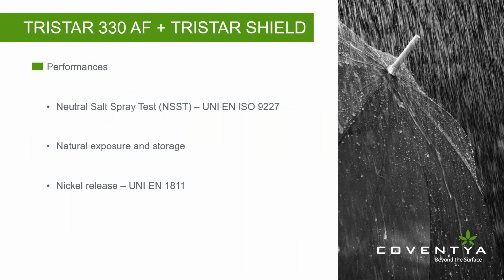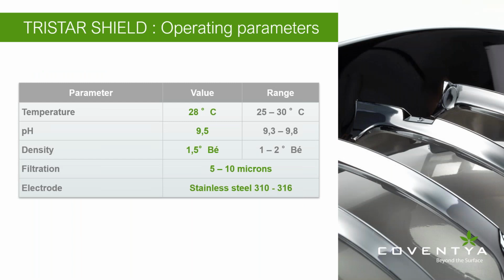These are the tests passed thanks to the combination of Tristar 330AF and Tristar Shield: neutral salt spray test, natural exposure and storage, and nickel release. The table recaps the working parameters of Tristar Shield. It works at 28 degrees, 9.5 pH units. It has a density of 1.5 degrees Baumé, and the anodes to be used are stainless steel 310, 316. We also recommend solution filtration. The passivation is electrolytic. In this case, Coventya supplies the rectifier to ensure process performance.